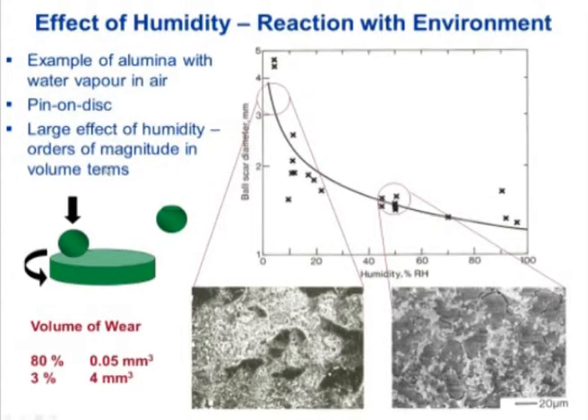And there's a huge effect, in fact. If you look at just the effect on the wear scar, that goes from about 1.5 millimeters up to nearly 4.5 millimeters. And that doesn't seem quite as bad. That's only a few factors. But if you actually convert that to the volume of wear that takes place here, then there's a huge difference between 80% humidity, where the volume is 0.05 cubic millimeters, and 3% humidity, where it's 4 cubic millimeters. So several orders of magnitude.